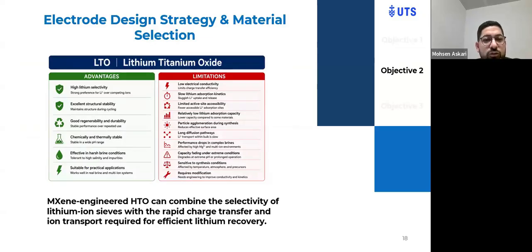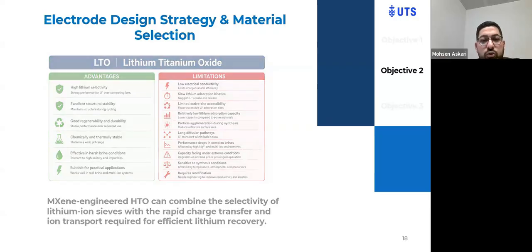We selected lithium titanium oxide, LTO, since it has high lithium selectivity as a lithium ion sieve material, excellent structural stability, and good regenerability and durability, while it suffers from low electrical conductivity, slow lithium adsorption kinetics, limited lithium active site accessibility, and other weak points. So the hypothesis was that the MXene-engineered HTO can combine the selectivity of the lithium ion sieve with the rapid charge transfer and ion transfer required for efficient lithium recovery.